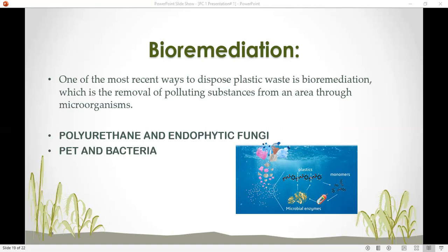Therefore, they were screened in other assays. These other experiments showed that Pestalotiopsis microspora and other genera are the quickest to degrade PUR as the sole carbon source in liquid cultures, and two are able to grow in anaerobic conditions.